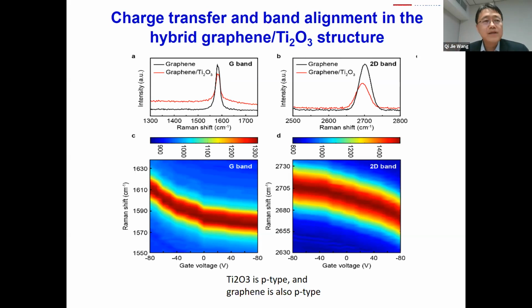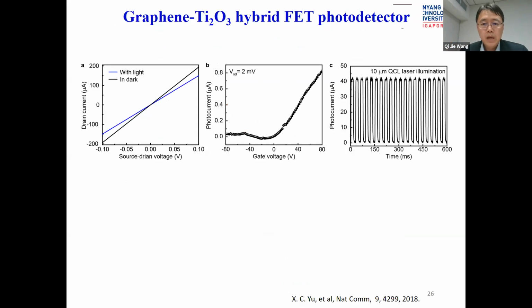But the good part is that we have this back gate in the FET structure, so we can gate the graphene layer to make the graphene an N-type material. With that, we can have efficient carrier transfer from the nanoparticle to graphene. So this figure basically shows that through Raman spectroscopy, we indeed can observe such carrier transfer. And indeed, in the device fabrication, as shown in the middle figure on the top, by gating the graphene layer, if we gate positively, and then this is in the N-type region of the graphene, we indeed see the photocurrent generated, while when negative voltage is applied, we don't see such a photoresponse.